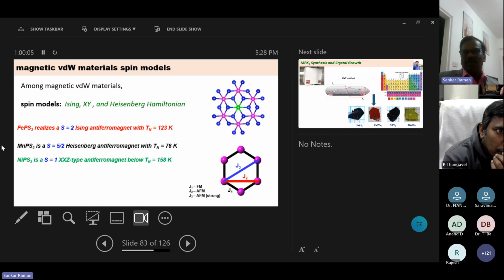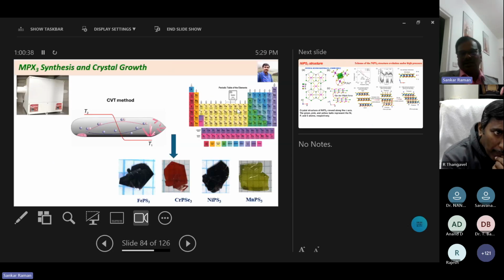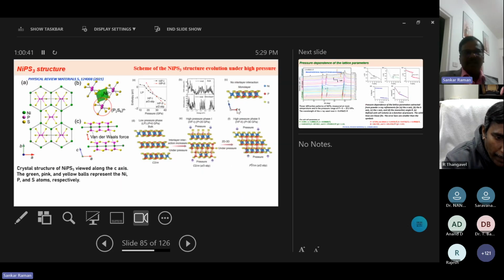You can see all the material in a honeycomb lattice, because in this honeycomb lattice, J1 is the nearest neighbor atom, second neighbor is J2, third one J3. Already I informed you, if you create a defect in this material, you can clearly see the green one is sulfur. Here J3 is via superexchange through sulfur. If you create the sulfur defect, this material sometimes shows a strong ferromagnetic nature also. These are all grown by the CVT method. Then NiPS3 belongs to D8 electronic configuration, with octahedral coordination.